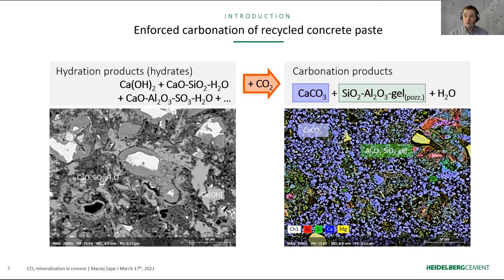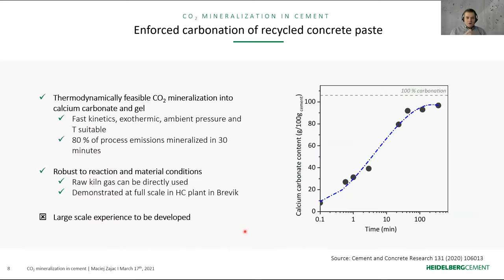During the wet carbonation, it is mostly calcite at normal temperature and pressure. And then you see this greenish area; those are the relics of the cement paste grains, which are basically now this alumina silica gel. There are two very important pieces of information related to this carbonation reaction. The first one is that it is a rapid reaction, and this is particularly important. It is rapid at normal temperature and pressure, and we are able to achieve 80% of the reaction after only 20 to 30 minutes. Please note, still at 20 degrees Celsius and at normal atmospheric pressure.